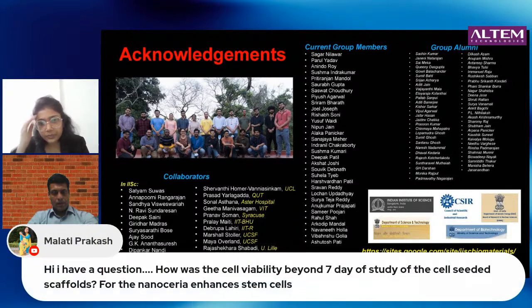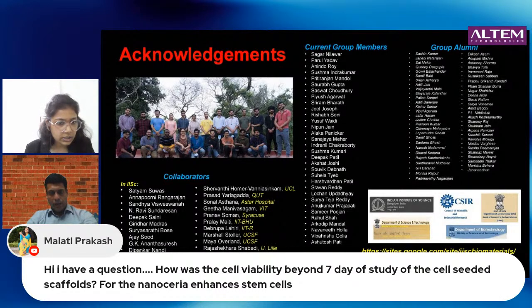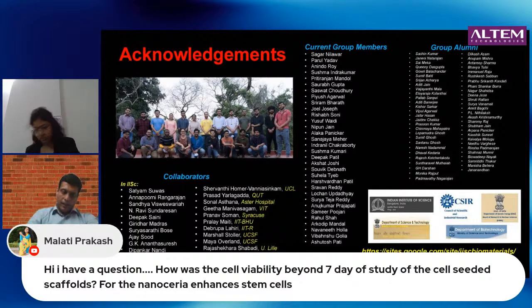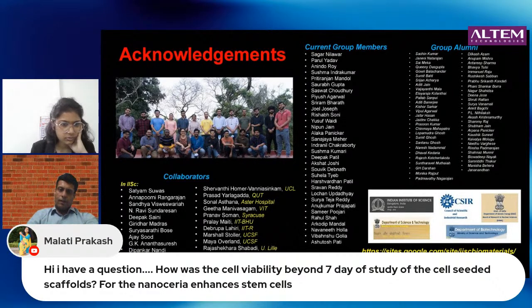Okay, so there's one question which is, how is the cell viability beyond 7 days of study of the cell seeded scaffolds? This is specifically for the Nanoceria enhanced stem cells. Yeah, so actually, for most of these materials, we found that the viability and the growth are all great. As long as you start with polymers that are non-toxic, and something like polylactic acid, of course, is non-toxic. It's widely used in biomedical applications, so the cell growth is fine. Nanoceria as a material itself is also non-toxic as long as you keep the concentration low. And since we just modified the surface of the scaffold, it was not toxic, and it also supported the cells.